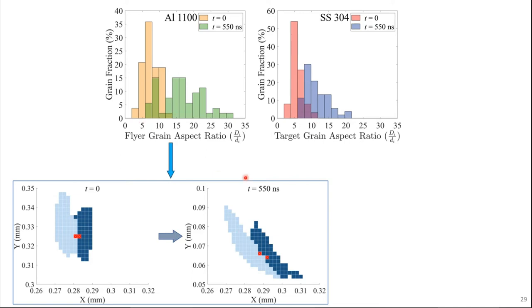This is quantitative, so to give you a better visualization of what's actually happening, we took two grains which share a boundary, and we marked two volumes or two Eulerian points just to see how far apart they would stretch during the simulation. At T equals 0, they align, but at T equals 550, these points have separated. And that just shows us that you have this stretching and shearing occurring, or grain boundary sliding occurring at the boundary or at the interface between these adjoining grains.